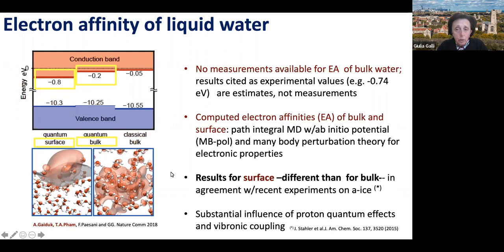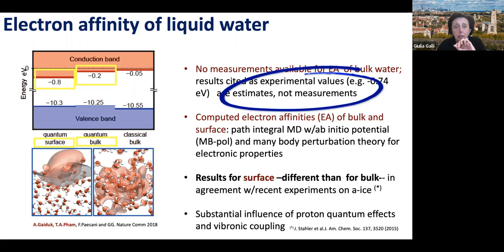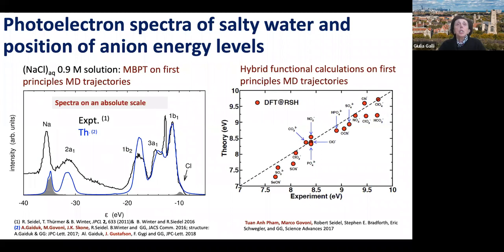But instead of telling you exactly about the numbers and what we obtain, here I want to make a point that the electron affinity of water experimentally is not yet settled. That number is not yet settled. The electron affinity has never been measured directly, and there are only estimates. So we are working with a comparison with estimates carried out experimentally and not with real numbers. This is important, very important to understand, because there are many instances in this complicated field where there are numbers that you see in the literature as measurements, but these actually are estimates. And so we have a computational number for the electron affinity, which is consistent with the best estimate that we have experimentally. The situation is different for the onset of the photoelectron spectra.